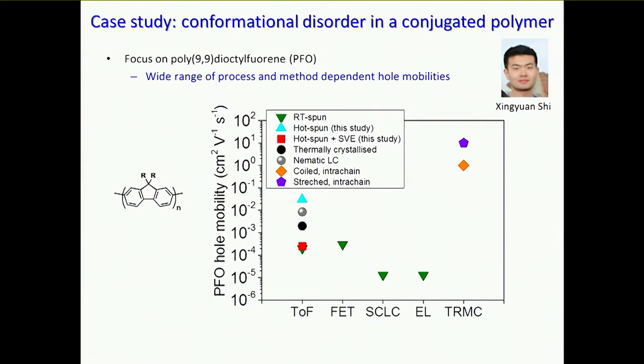So the preliminary measurements, we've seen FET mobilities more around about 10 to the minus 2 when we think that the beta phase is absent, but we want to repeat that, and so that's why I'm not talking about it now. Okay, is that okay? Yeah, yeah. Okay. If you like, I've got much less confidence in the reasons for that number than I do for the ones that we've done in a more systematic way.